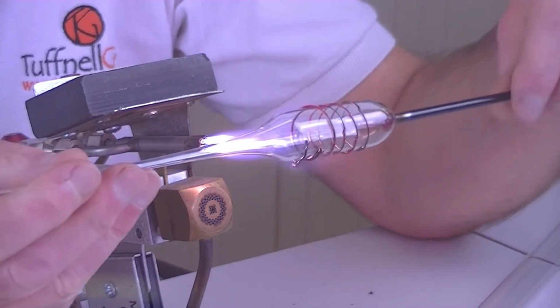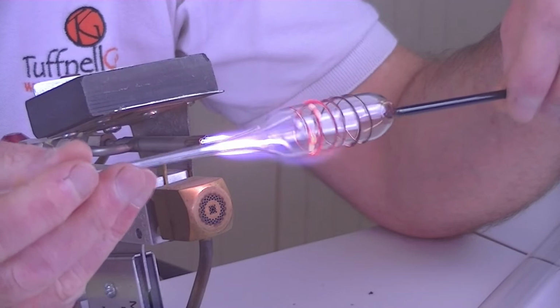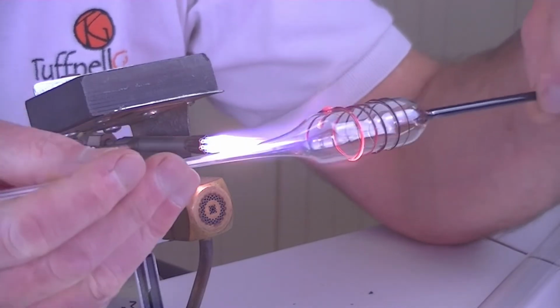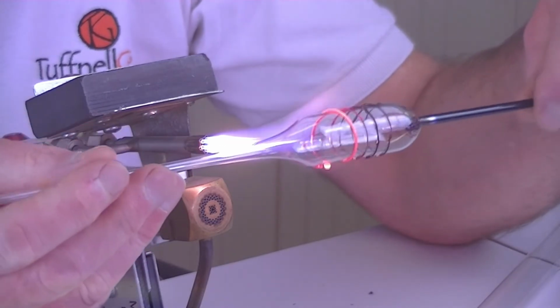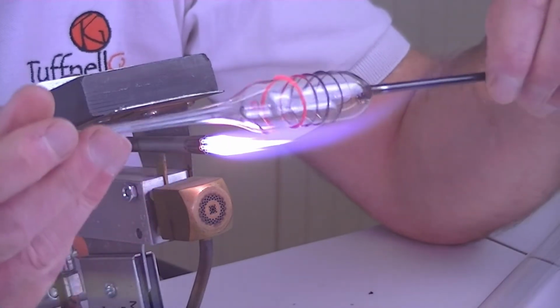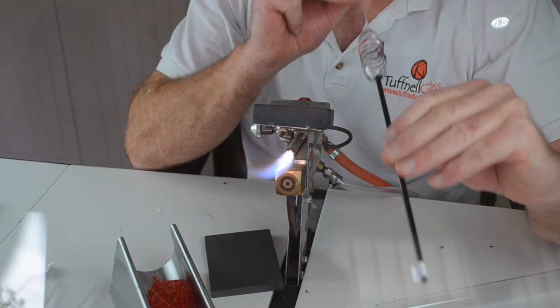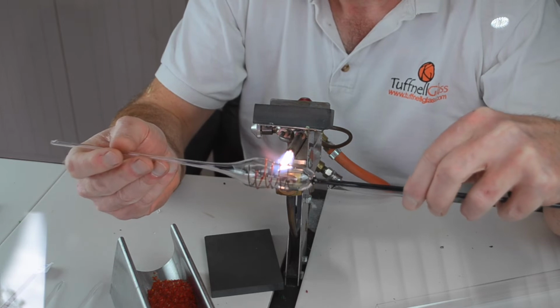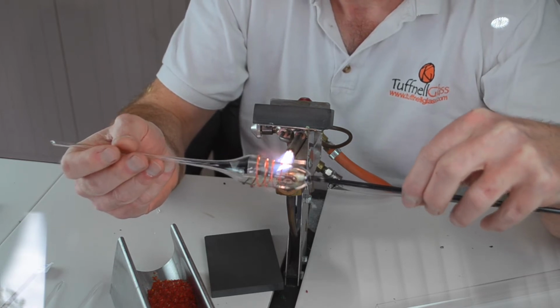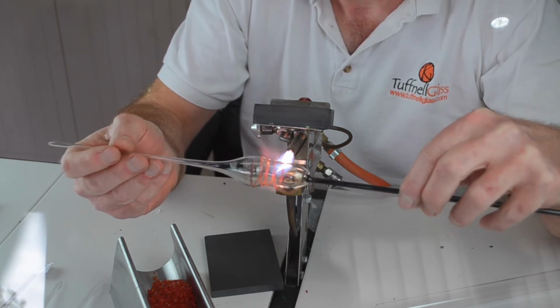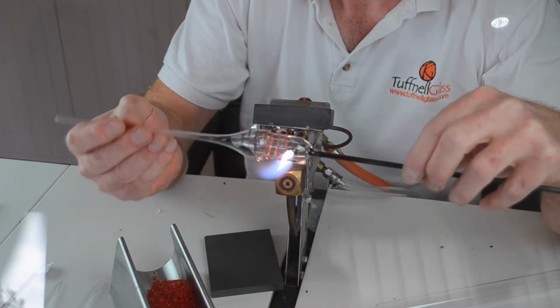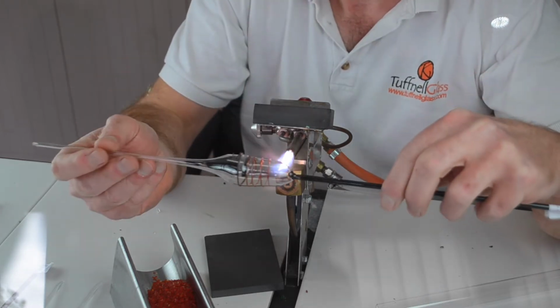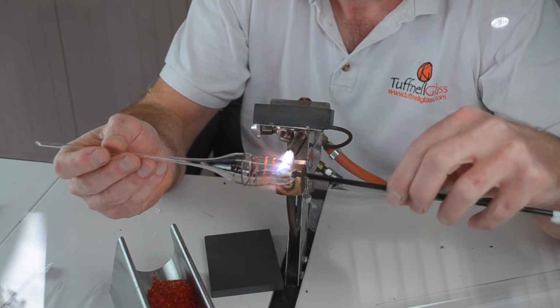And so as you start to work towards blowing the bauble, you need to think, at the moment the glass is relatively thin, so it's about 1 millimetre thick. You don't want to blow that up straight away, because it gets thinner the more you blow it. So when you're starting with a wall of say 1 or 1.2 millimetres, by the time you blow it up, it's going to end up about 0.5 millimetre, so it's very fragile.